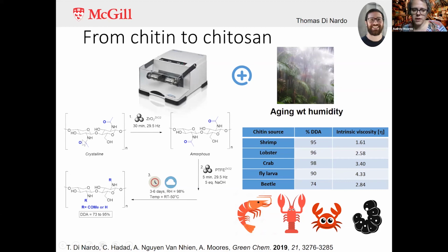So here we did this from chitin, but we also showed that we could use even powder from crustacean shell directly, or even insects. And we get very good results in terms of deacetylation, which is the marker that will tell us that we have made chitosan. We want something in the 90s, and as you see here, most of them give that. And a high intrinsic viscosity here is an indication of how long the polymer is, and this means that we have really, really long polymers. Again, something that is unusual to find for this reaction.